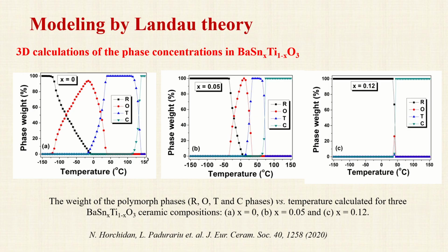The rhombohedral phase is present towards minus 20 degrees Celsius, and the orthorhombic phase does not vanish at minus 90 degrees Celsius. Even the tetragonal to cubic phase transition does not occur at a single temperature value, but is characterized by a range of transitions. The Landau approach describes correctly the shift of the transition temperatures in tin-doped barium titanate and describes the quadruple point for x equals 0.12.